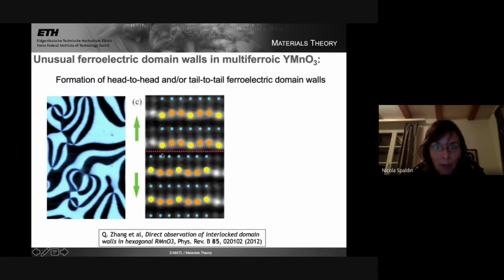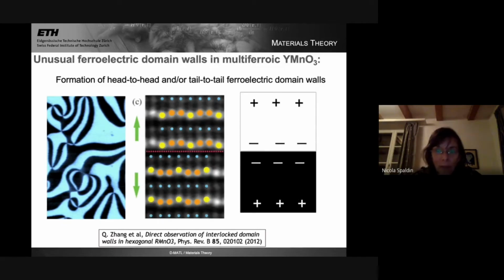It's very beautiful. And the pattern, when one has up, down, these are the yttrium ions. This is representing up polarization. And when one has down, up, this is representing down polarization. This is how, in the ferroelectric state, these planes of yttrium ions we looked at earlier kind of buckle and make the dipoles. And so if you remember your basic introductory electrostatics class, this means you have a dipole pointing up in one half and a dipole pointing down in the other half.